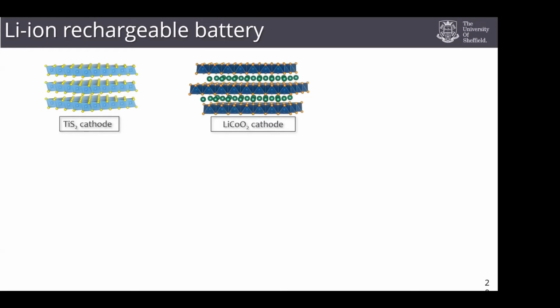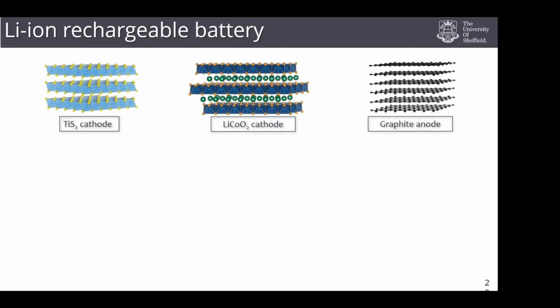And this really was coming at it from a solid state chemistry point of view and looking at the energy of your cobalt and your oxygen, and whether or not you could make a compound that had lithium in it, and then you could extract the lithium and charge and discharge that way. And then Akira Yoshino had thought about using graphite as an intercalating anode, intercalating meaning that you can slot those lithium ions into and out of that structure.